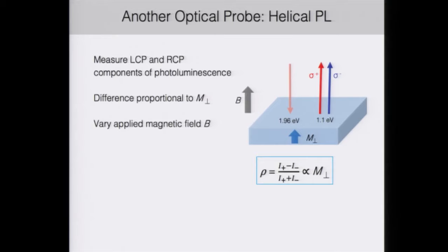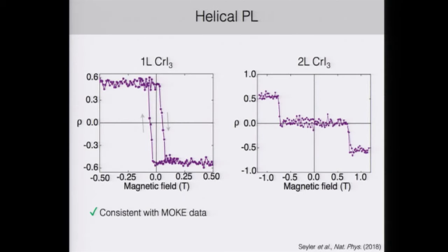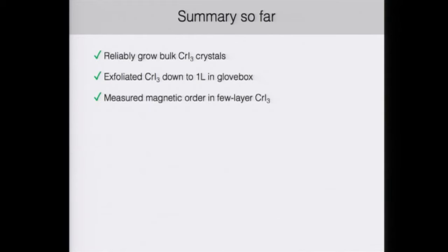In this case, we excite the material using a laser, and then we collect the right and left circularly polarized components of the photoluminescence that are emitted from chromium iodide. This difference in the right and left circularly polarized components is also going to be proportional to the out-of-plane magnetization. Again, we can apply an external magnetic field to change the magnetic states. Using helical photoluminescence, we're able to reproduce the same curves as we did with MOKE, which is consistent with our MOKE data and verifies this signal.